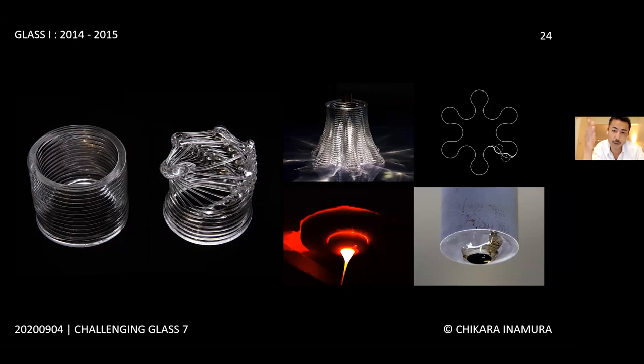Furthermore, a close examination of the initial products also revealed consistent deviation at the inflection point of every curvature. This is likely caused by a twisting of a molten glass filament. The internal capillary force of molten glass provides an ability to relax the external shear and torsional force applied to it. But once this external force exceeds the capillary force, it will no longer retain its original shape and the product will deviate from its original path.